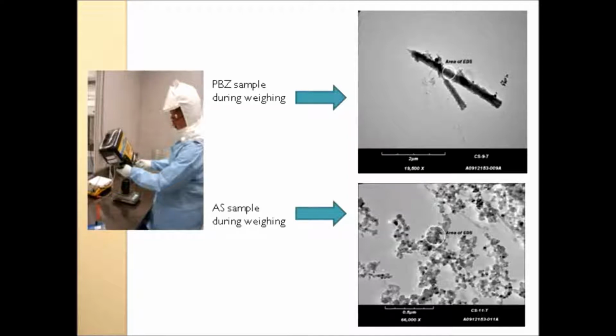Here he's using that special device that he's fabricated to transfer the material from the trays, the homogenizer, the blender, into a weighing flask. And you can see he's protected. He's got a powered air purifying respirator on with a hood. He's got gloves, sealed at the wrist. He's got a disposable lab coat. But if he didn't have that on, his personal breathing zone sample showed that there is material migrating from here, which is the beaker, up into this region, because he's got a sampler sitting right there. Again, the at-source sample, which is partially obscured, is actually on a ring stand behind the beaker. So it's in that real close general vicinity. You can see that there is a lot of material that does come off when they do that operation.